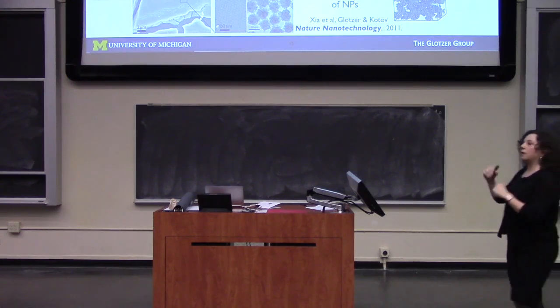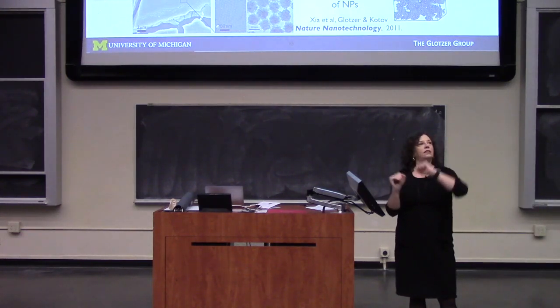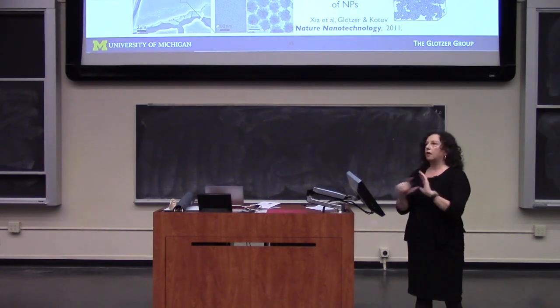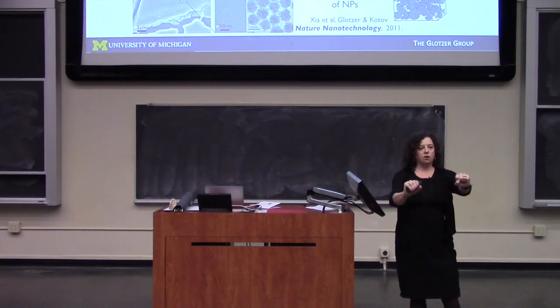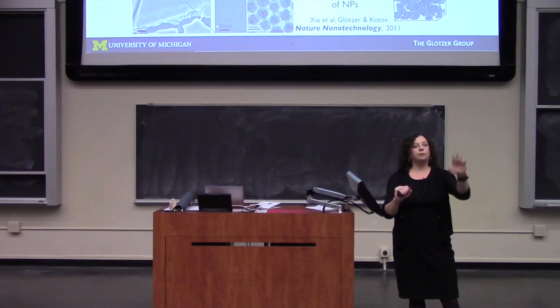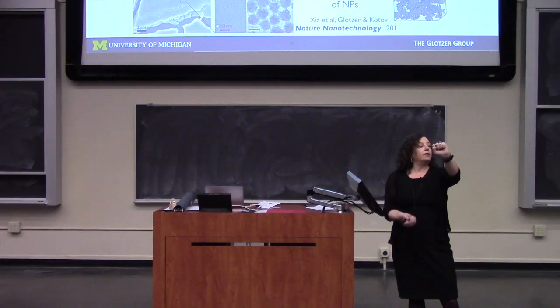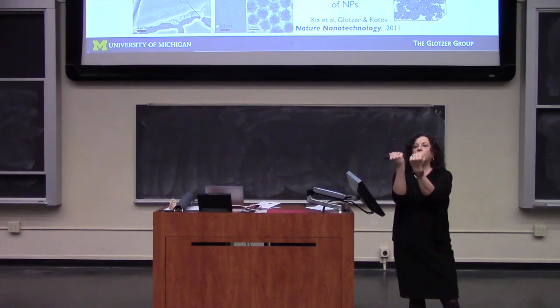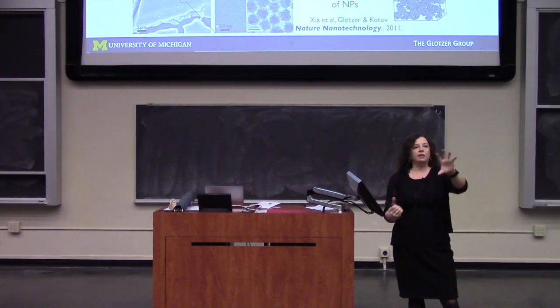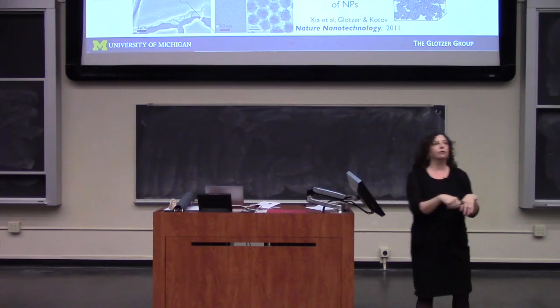So we're using Monte Carlo simulations because that's really easy to do with hard particles. And the algorithm could not be simpler. You randomly choose a particle, and you try to randomly rotate it a tiny bit or translate it a tiny bit. Now in regular Monte Carlo, you would calculate the change in energy, and if the change in energy is negative, you do it, and if the change in energy is positive, you do it according to some Boltzmann probability. For us, with these hard particles, either there's no interaction or there's an infinity of energy, because they just can't overlap. So for us, it just means if the particles don't overlap, we do the move. That's all.